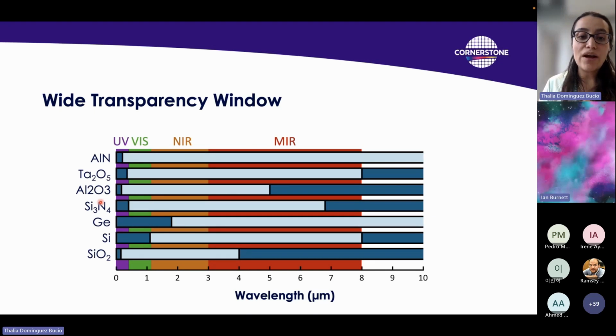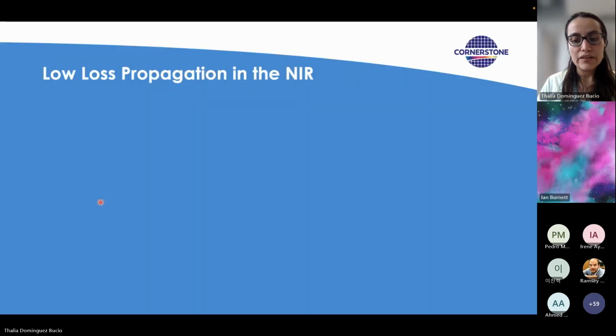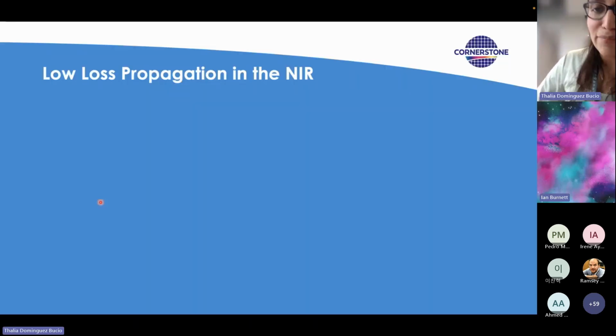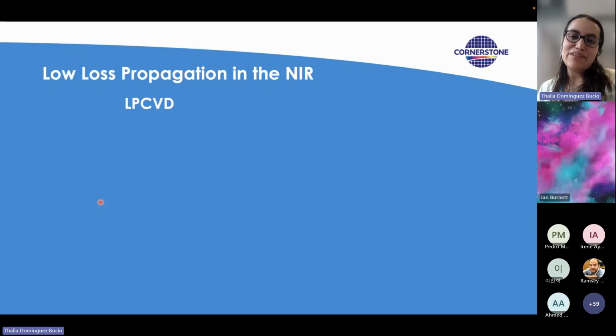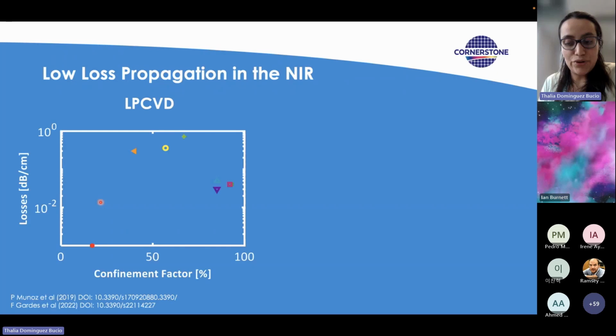Now, this opens a wide range of possibilities for silicon nitride because you can use it for applications in which you require near-infrared wavelengths, you can use it for the mid-infrared, you can use it for the visible, or you can use it for applications in which you will cover all these wavelengths. Because the material is transparent, both in the near-infrared and the visible, that means that we can achieve low propagation loss. Again, as I mentioned before, there are two different types of losses. We have the LPCVD losses and the PECVD losses. This is important because one material will have ultra low losses and the other one won't.